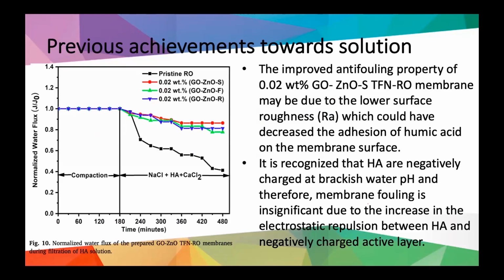The aim of this work was to see the effect of fouling using a fouling solution composed of humic acid, calcium chloride, and also sodium chloride. Here are the four types of membranes: the pristine membrane, which is free of anything and represents the commercial one, which we also prepared in our team with no additions, compared with the ones with zinc oxide nanospheres, nanoflowers, and nanorods. We then went through a compaction period of about 3 hours.